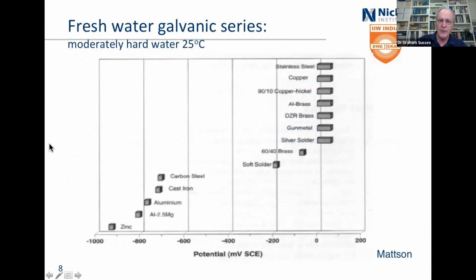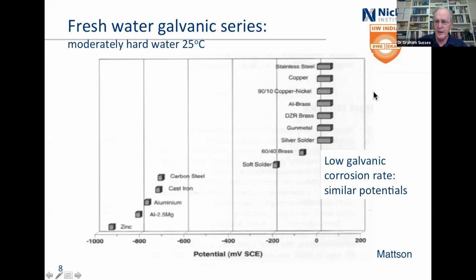This is in freshwater, moderately hard water, 25 degrees C. And it's a bit different, but here, look, stainless steel, copper, 90/10, Al-Brass, dezincification resistance, so it's got a little bit of arsenic in it, gunmetal, silver solder, all about the same potential. So in moderately hard water at about 25 C, those won't corrode against each other. Low galvanic.